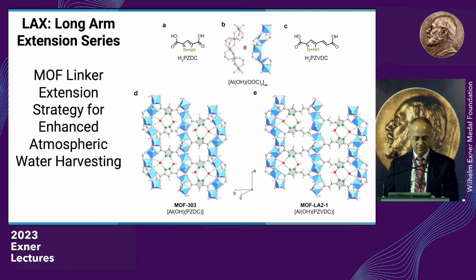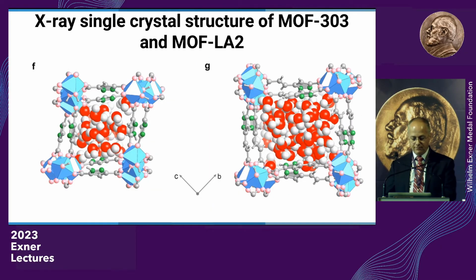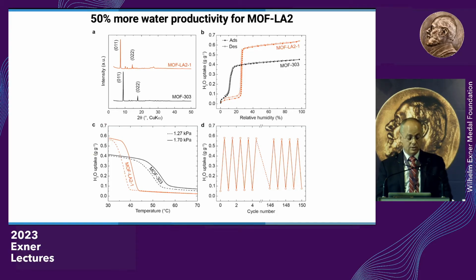Okay, this is MOF 303 on this side. This is the new MOF, LA2, meaning long arm extension with 2 carbons. And you see here that it's taking up 50% more water than MOF 303. And furthermore, the desorption temperature of water is much less. It goes from almost 55, 56, down to 45. So you're even using less energy to take water out of the pores.